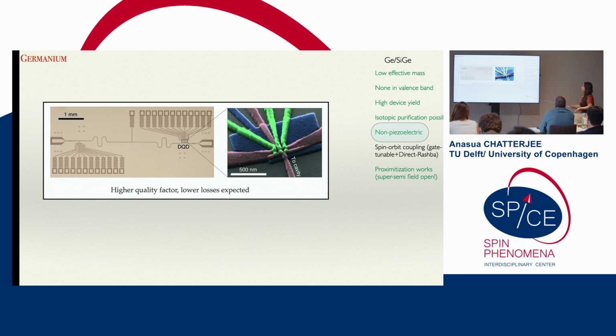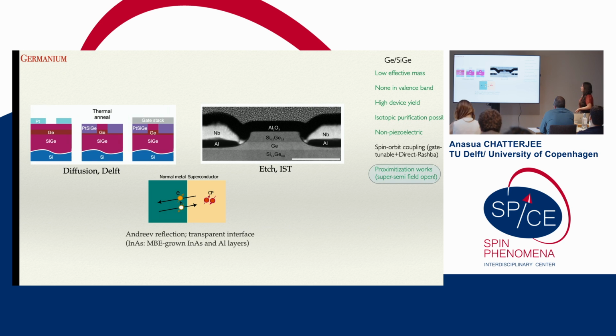In terms of non-piezoelectricity, we expect that there's lower losses from making resonators on top. There are some hints in the field that there may be other things limiting the quality factor of resonators, but we hope we can get over this, but at least it's not piezoelectric. And lastly, the idea is that if you have the Fermi level pinning that you have in these germanium structures, you should expect to have proximitization working. But of course, it's one thing to proximitize a material and another thing to do it in a clean way such that you have this Andreev reflection and a transparent interface. Because that's really what you need for many of these kind of quantum coherent applications.